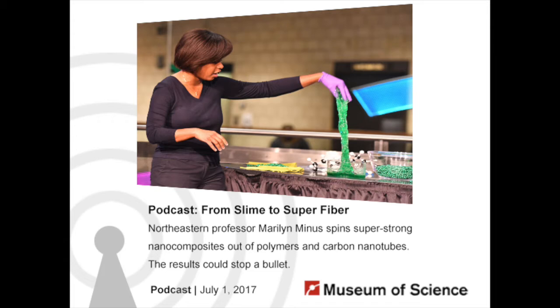So that's the thing with polymers. Polymers prefer to be tangled up and they prefer to be jumbled up with each other. They don't really like laying straight. So to get them to do that, we almost have to trick them into doing it, or provide exactly the right conditions where they say, okay, this is the structure I prefer. So how do you trick them? We trick them by using different temperatures. The temperature at which you treat the polymers can actually cause them to want to be in alignment with one another. Then you also have to put an additional force on them that'll push them in the direction you want them to align. And I do that by using flow.